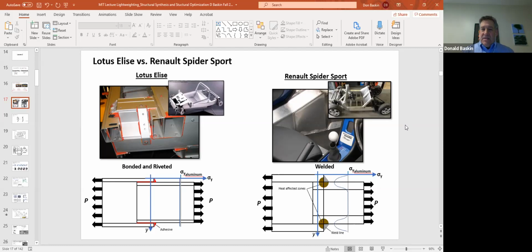The butting is what it is: they use a thicker wall section at the place where the weld takes place in the steel. And then they thin it out as you go along the tube. So the tube has a varying wall thickness. At the ends where it gets welded, it's thick. And then for most of the center, it's very thin.